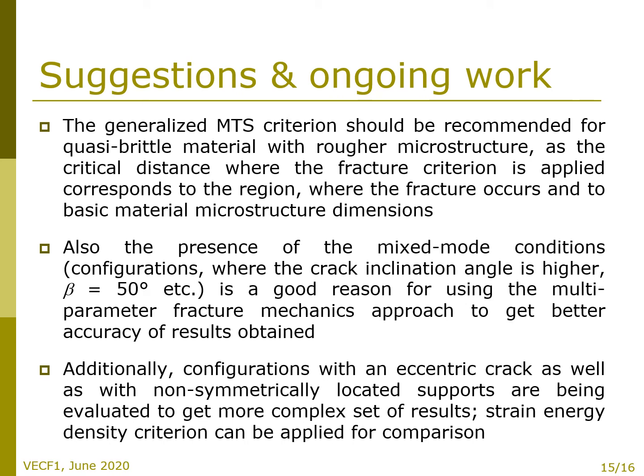When more general conclusions and final suggestions shall be made, it can be stated that the generalized MTS criterion should be recommended for quasi-brittle material with rougher microstructure, such as concrete, as the critical distance where the fracture criterion is applied corresponds to the region where the fracture occurs and to basic material microstructure dimensions. Also, the presence of the mixed mode conditions, configurations where the crack inclination angle is higher, beta is equal to 50 degrees, and so on, is a good reason for using the multi-parameter fracture mechanics approach to get better accuracy of results obtained.